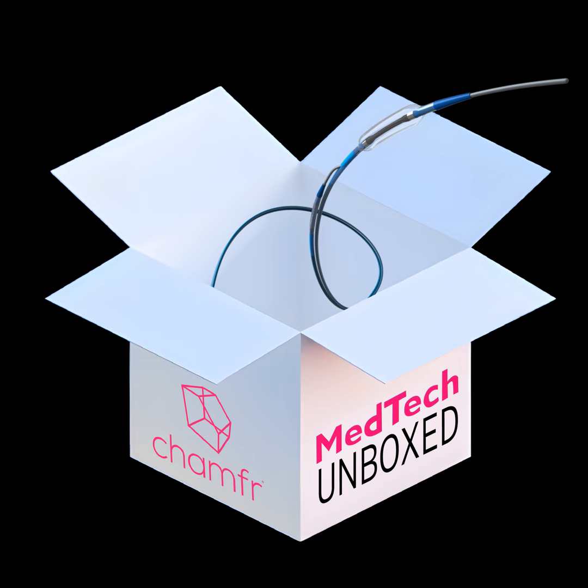Because a material like EverGlide Plus we discussed, the early example was a 60D version. So now I can actually do a 20D version of that liner for that specific type of application. And the flex modulus is only like 5 times, or less than 10 times, that of PTFE. So now you have a choice to get the distal end of your catheter more flexible than your competitor. So I think this is really where the lower durometer or different durometer choices of liner give R&D engineers more flexibility, not just focusing on the jacket or the braid or the laser cut hypotube structure.